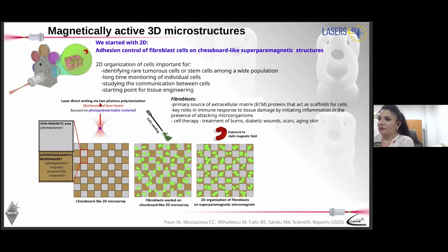In brief, what we did, we used the 3D printing technique that I told you about in the beginning of my presentation. Then we made a chessboard-like structure where you have here the gray squares with just photopolymer, non-magnetic, which was alternating with the brown squares that were magnetic, because here was photopolymer blended with superparamagnetic nanoparticles.